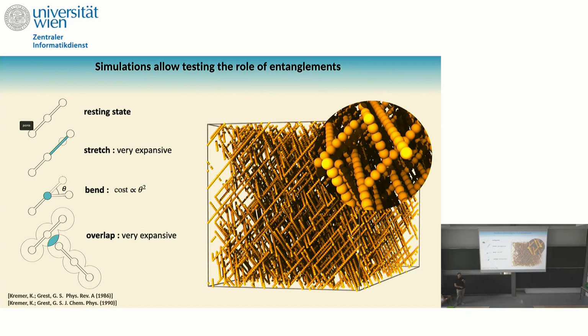This goes back to your question, I guess, how we form a branched actin. It's the same general scheme that I showed you before. What I need to tell is just the interaction between the particles. But here, on top of that, I will link the particles together by bonds. I will not let them self-assemble the way they want to self-assemble, because I want this branched-like structure. So I start from a branched-like structure, and then I put links between the particles. So this is the resting state.